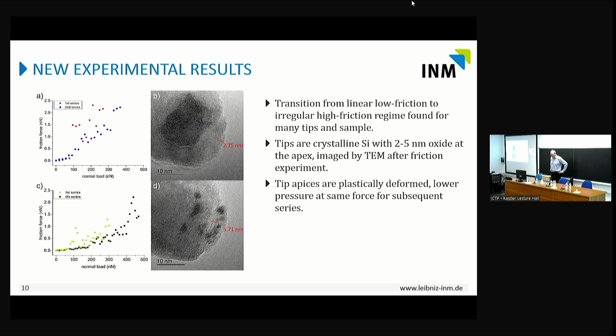We have done this again and again, and we find that if you take a fresh tip from the box, a super sharp oxidized tip, and you do this experiment, the transition is actually around 80 nanonewton. If you do the same experiment a second time, the transition is already at 90 nanonewton. So the more often you do the experiment, the higher the transition. Obviously we are flattening our tip and the pressure is going down.